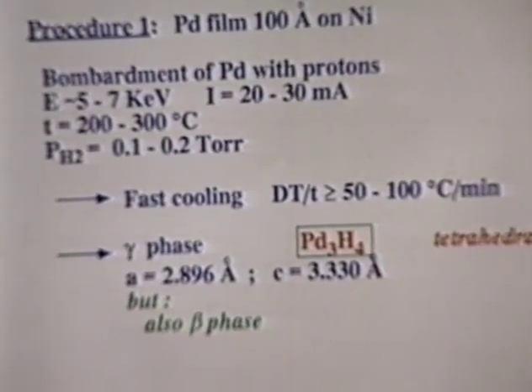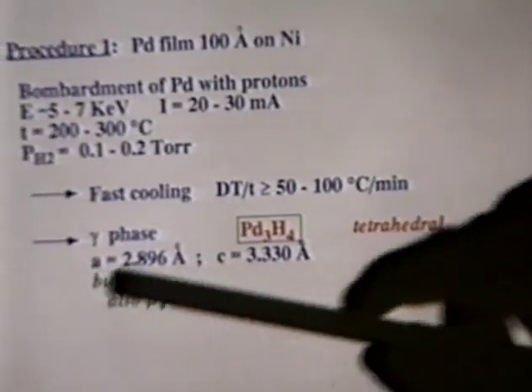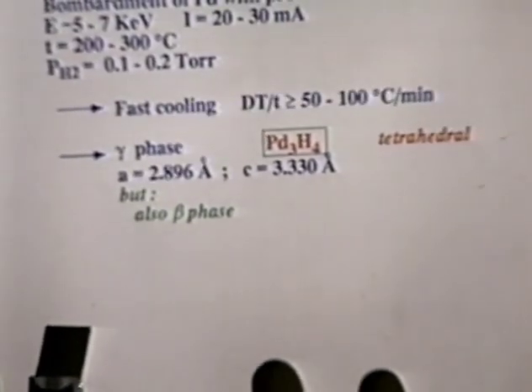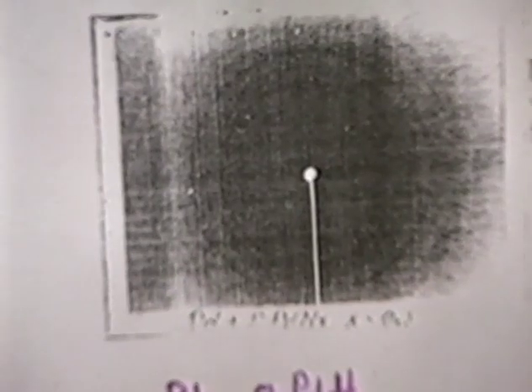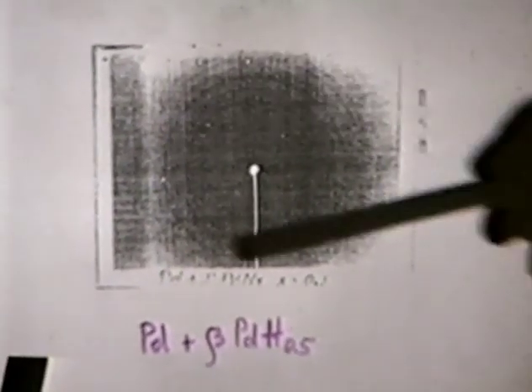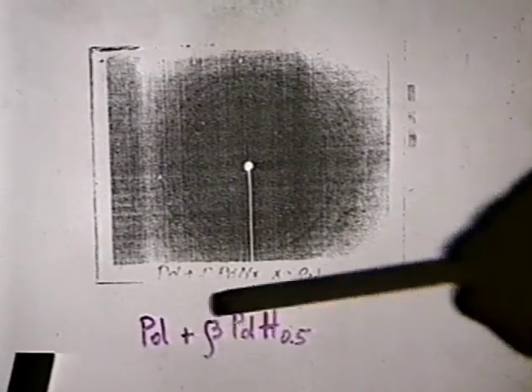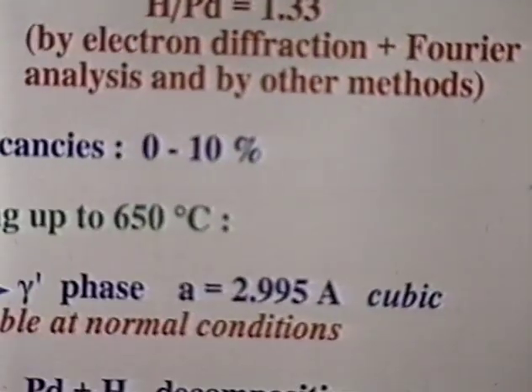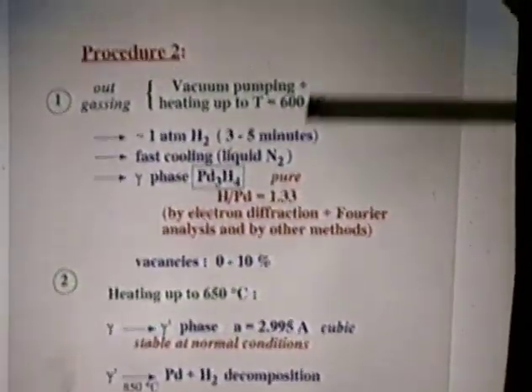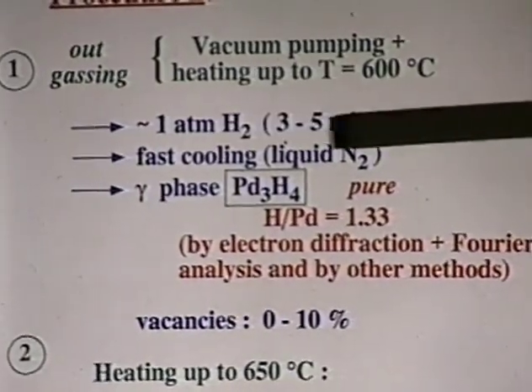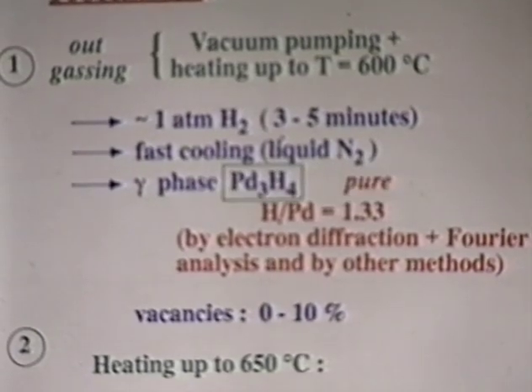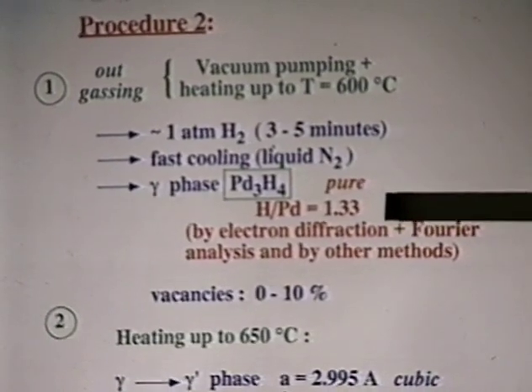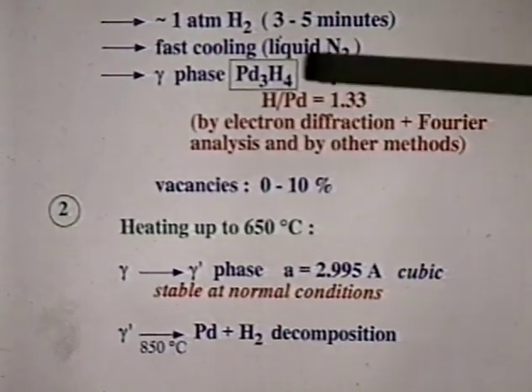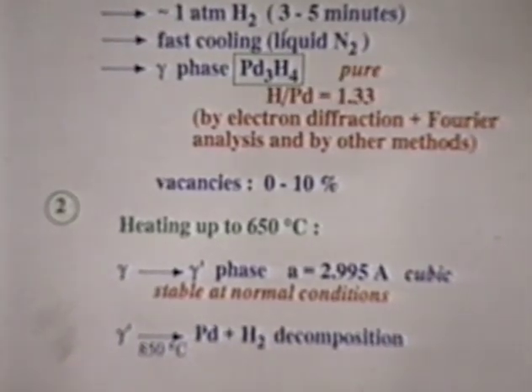What is achieved is Pd3H4 in a tetrahedral structure, but it's a mixed state with also beta phase. Not only gamma phase tetrahedra, but mixed, and with diffraction you wouldn't see the diffraction rings, but some confused pattern because it's at the same time gamma phase and beta phase. With the second procedure, which is this one, outgassing, and then a few minutes in hydrogen, and then fast cooling with liquid nitrogen, you achieve gamma phase, a very pure one, I will show it, and this is exactly the 1.33 ratio because it's this hydride.